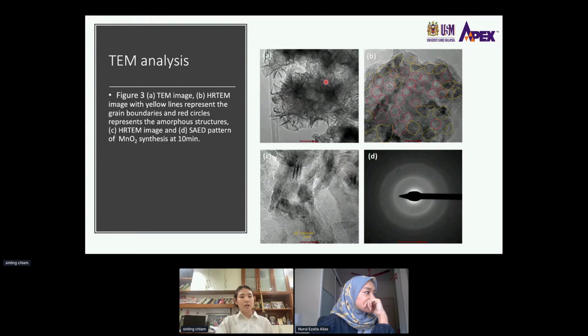Next, this is the TEM image of the MnO2 particles synthesized at 10 minutes. It is composed of wrinkled and intersected nanosheets that self-assemble and finally grow in all directions to produce MnO2 nanoflowers. From HRTEM, we can see short and non-continuous lattice fringes distributed all over the structure, as highlighted in yellow. Besides, most of the region lacks lattice fringes, which indicates that the MnO2 nanoflowers are amorphous. This observation is aligned with our XRD analysis earlier. Next, the SAED pattern also exhibits diffuse rings, again indicating the amorphous characteristic of MnO2.